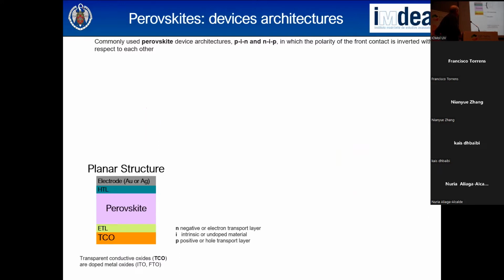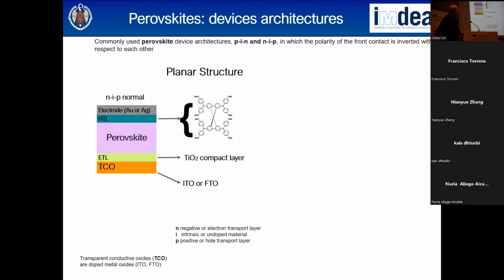Perhaps the most typical is the planar structure. This is what is called the NIP. N is the negative or electron transport layer, and this is the way in which the device is fabricated. Then the I, which is the intrinsic or undoped material, and the P, the hole transporting layer, which is the positive or hole transport layer. This is the famous Spiro-OMeTAD, about which I will tell you a little more later on, a molecule which is considered as the best one. And the reason this happened, with the PCBM in fullerene chemistry,